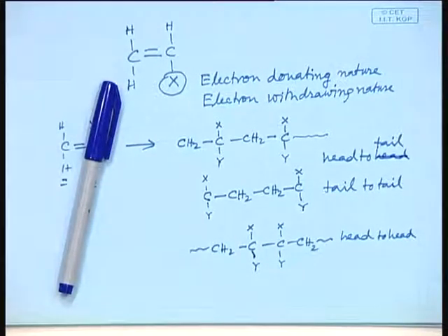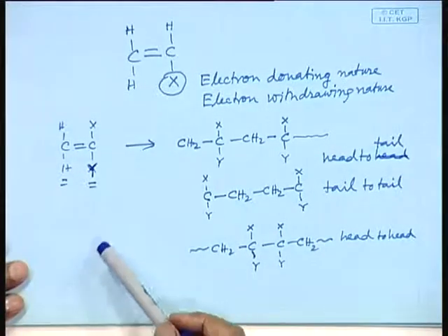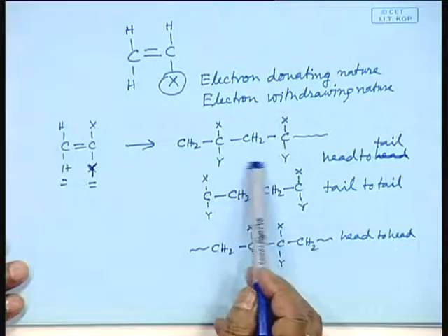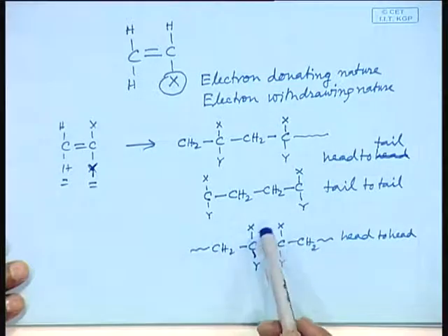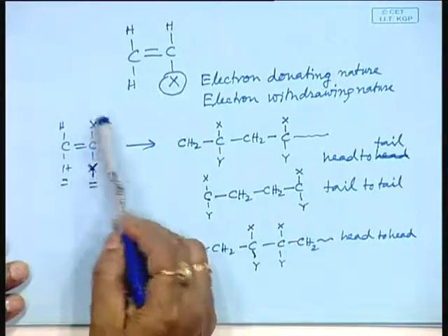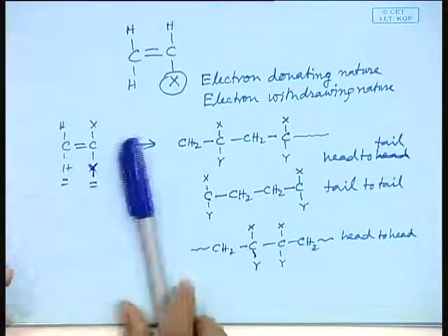When will it happen? Shift of charge or this radical addition, that is a different thing, but here you have to consider the steric aspect. Now, that depends on the size of these substituents. So, bigger substituents will hinder this kind of addition, whereas that will augment this kind of head to tail addition. So, that depends on the size of the substituents present in the monomer structure.